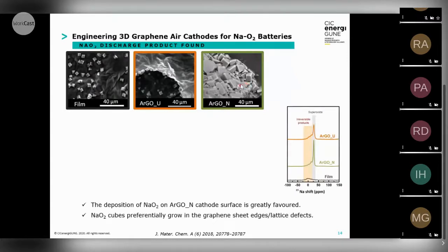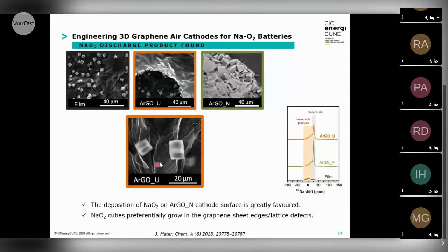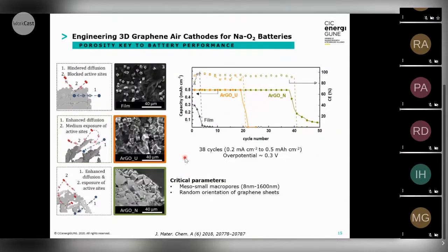We confirm this by NMR, that we have sodium superoxide, and also we found that these cubes preferentially grow on the graphene sheet edges or the lattice defects, which are more active. And we came up with this schematic, which explains the difference in the cycling performance, because with the one freeze dried at minus 196, we can get a longer cycle life.